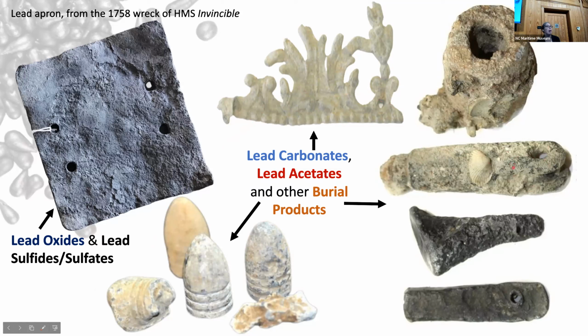So these are artifacts that have come from a burial environment, and they are covered in a dense concrete-like material that we call concretion, which is essentially natural concrete, which forms on metal artifacts, often in burial environments. So as you can see, a lot of this material, though in some instances it actually produces a very even, almost nice patina surface that can be very attractive in its own right, can, because it is more voluminous, tend to disguise or obscure this information.